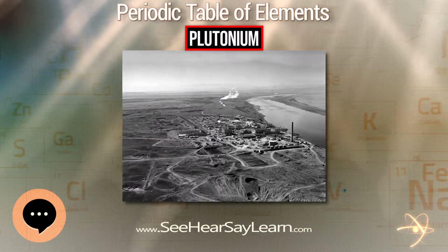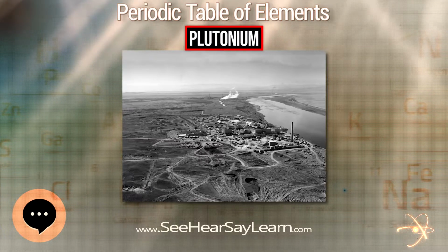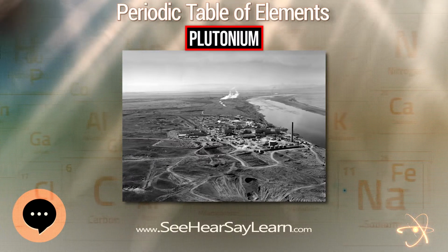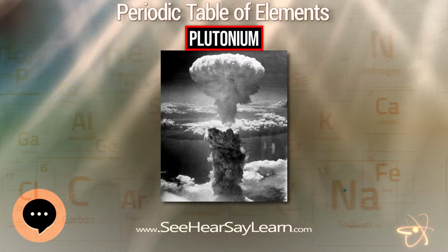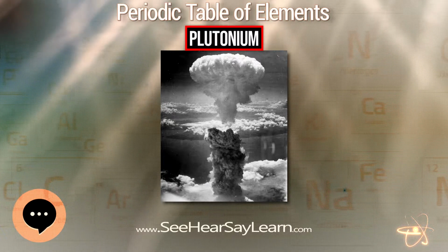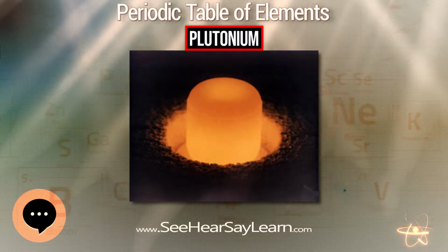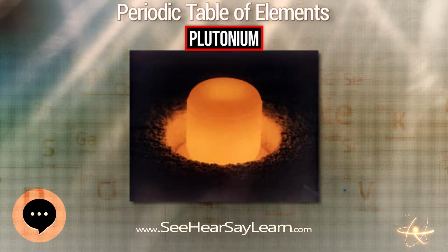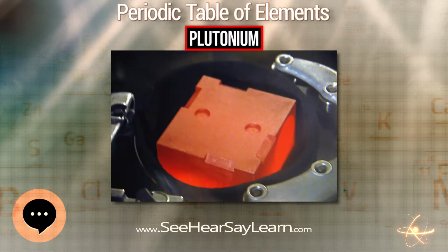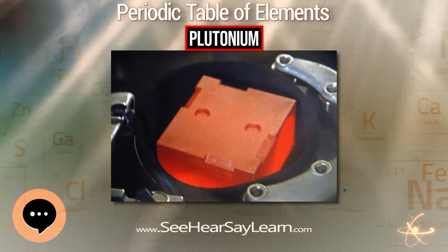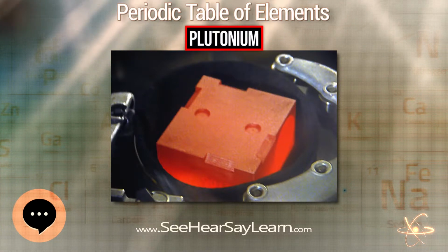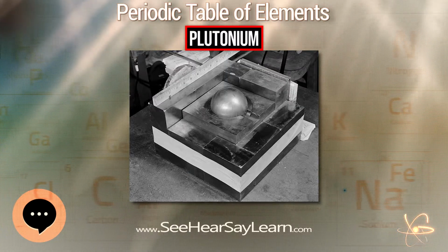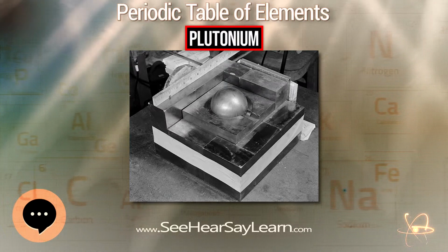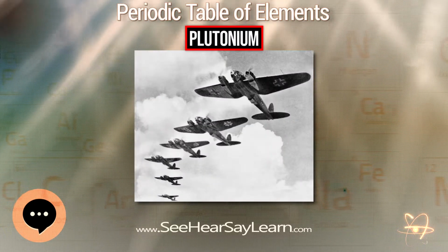For example, the alpha form exists at room temperature in unalloyed plutonium. It has machining characteristics similar to cast iron but changes to the plastic and malleable beta form at slightly higher temperatures. The reasons for the complicated phase diagram are not entirely understood. The alpha form has a low symmetry monoclinic structure, hence its brittleness, strength, compressibility, and poor thermal conductivity.